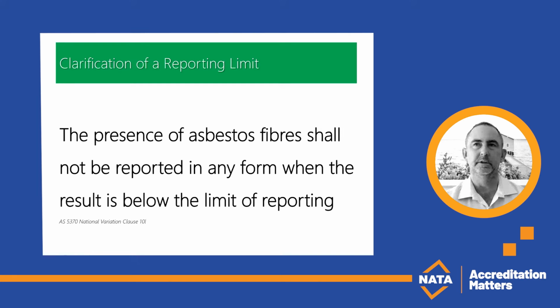The Standards Committee had thoroughly investigated this issue and concluded that results below the reporting limit of 0.01% weight per weight are essentially meaningless. If lower detection limits are deemed necessary, a separate standard should be developed through the Standards Committee for a specific purpose. This would require advanced techniques and rigorous scrutiny, especially regarding sampling areas. However, this already exists in the form of the NEPM, which acknowledges that 0.01% is still fit for purpose.